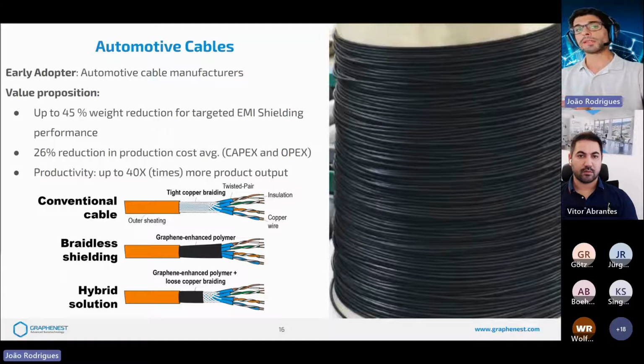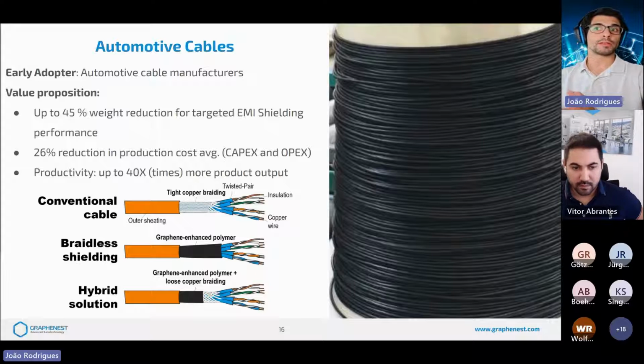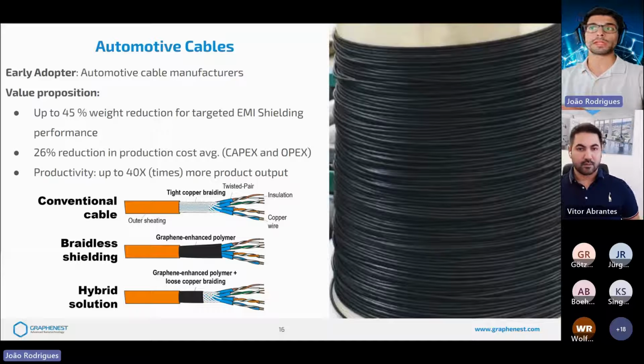But based on the final requirements for your cable or the application where it needs to be used, there are two alternatives. You can go for the braidless shielding, so basically remove all the metal shielding and place a graphene enhanced polymer. But if you require even higher performance in terms of shielding, you can opt for a hybrid solution, where you use just a loose copper braiding, so you use less material with a bigger aperture of this braiding, so it's quicker to produce and it uses less metal.